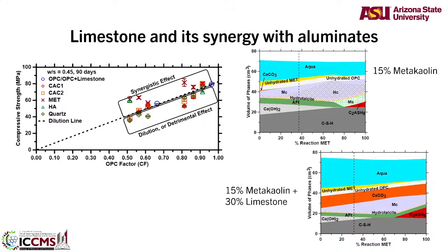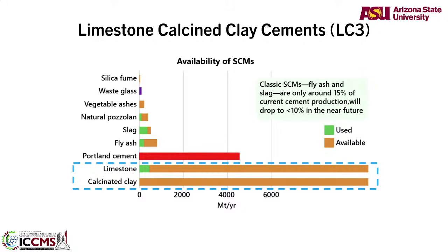And if you look at it here, you have pretty much reduced 50% of your clinker. Right? So that is a massive reduction in terms of cement. Again, this also talks about availability. Like I said, in the US, fly ash is not available much. This is the scenario of what we have. Silica fume, very little. Natural pozzolans, not much. Slag and fly ash, also very little. Plenty of Portland cement. But look at limestone, look at calcined clays, or I should say clays.